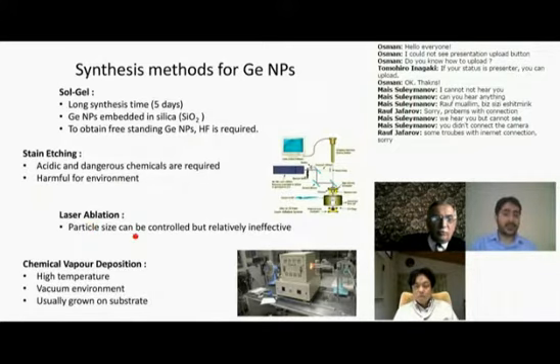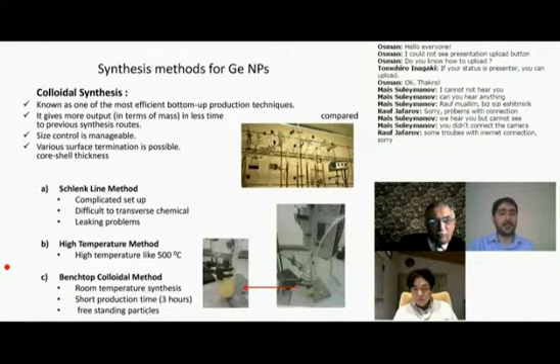In terms of laser ablation, it doesn't allow us to control the particle size. In laser ablation, we have our bulk material in a vial. We send a continuous laser beam onto it, and we can break down particles, but it's not efficient for getting a stable particle size. For chemical vapor deposition, there is a picture here from the lab. We have to go up to a high temperature like 500 degrees Celsius, and we need a vacuum environment and a complicated setup.